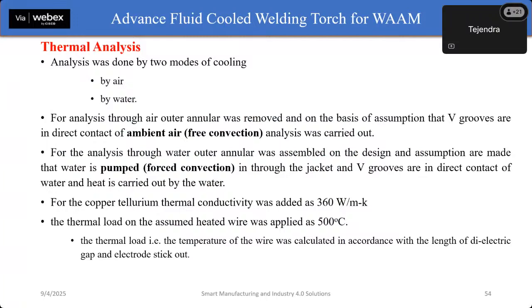The analysis in ANSYS was conducted using two cooling modes, air and water. For the air cooling analysis, the outer annular was removed and it was assumed that the V grooves were in direct contact with the ambient air, allowing for free convection. For the water cooled analysis, the outer annular was assembled onto the design with the assumption that the water was pumped through the jacket, resulting in forced convection. In this case, the V grooves were in direct contact with the water, which carried away the heat.